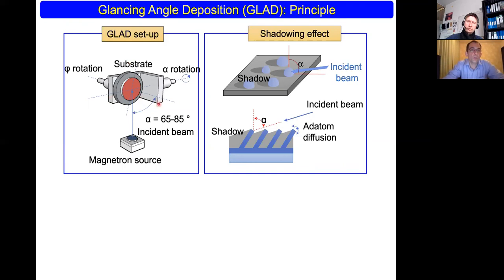And the most important part, this is the substrate holder, because we should precisely control two rotations. As shown here, this is the phi rotation. It controls the rotation in this direction. And the alpha rotation gives you the incident angle, the deposition angle, which is usually between 65 and 85 degrees.